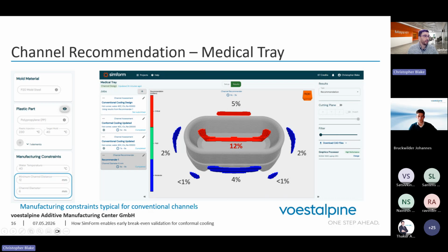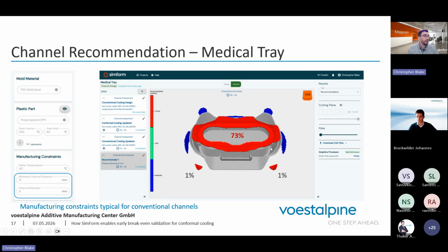And I'll show the underside of the plastic part. And it's not surprising that given the offset that we are forced to adhere to, given our conventional cooling techniques, the regions with the most cooling demand are in the concave areas of the plastic parts. These are the most important, where there's the narrow concave area inside of the medical tray. Overall, we predict a cooling time of about 8.6 seconds for this design proposal.